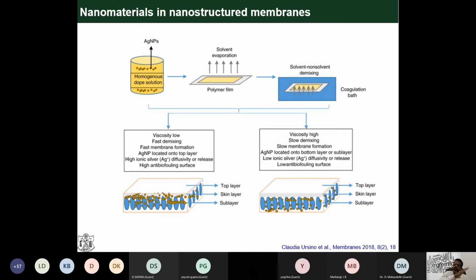But we mix this polymer and nanoparticle. This research work is with silver nanoparticles. The silver nanoparticles are located in the top layer of the polymer. If you have the nanoparticles in the top layer of the polymers, they diffuse or release, giving high antifouling property. But we need the nanoparticle distribution through the whole membrane. If the nanoparticles are uniformly distributed into the whole membrane, you get more chances for higher flux at reduced pressure. For that, the viscosity is high. Slow demixing, you control the evaporation of the solvent and slow membrane formation.